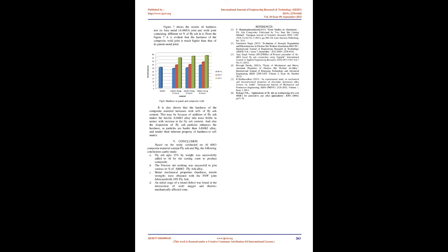And improvement in UTS may be due to the matrix strengthening that might have occurred following a reduction in composite grain size and the generation of a high dislocation density in the matrix as a result. Figure 6 shows the tensile strength of FSW joints increases gradually up to 10% fly ash, after that it decreases. The decrease in the tensile strength of the joints with fly ash weight fraction beyond 10% is due to the poor wettability of the reinforcement with the matrix.